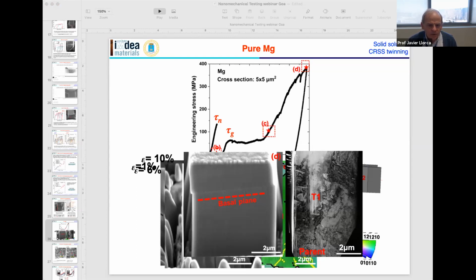And what we did is interrupted tests. Basically we carry out a test up to this point, then stop the test and look at the deformation mechanisms in the SEM, and also do TEM and transmission Kikuchi diffraction on thin lamellas extracted from the micropillar to see the orientation of the lattice at this point, point B, at this point that was point C, and at this point here that was point D. And this is what you are going to see.